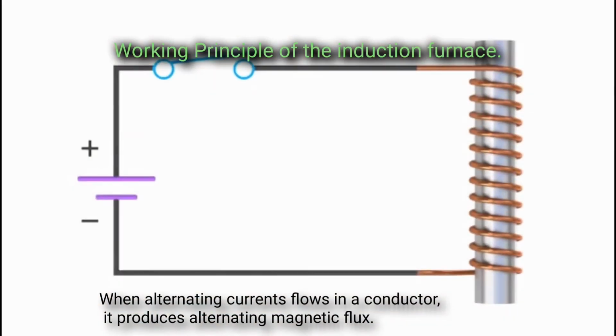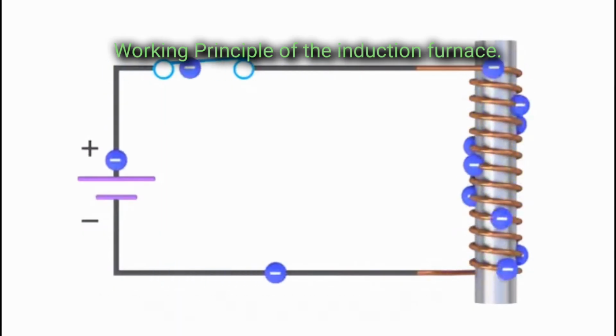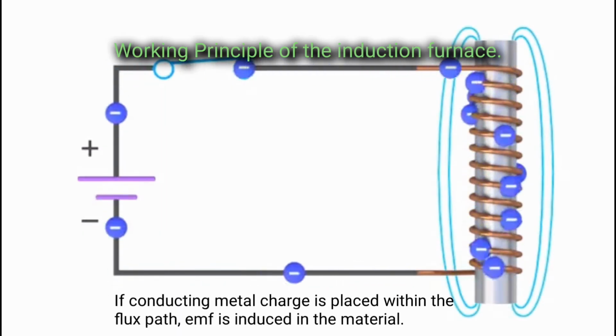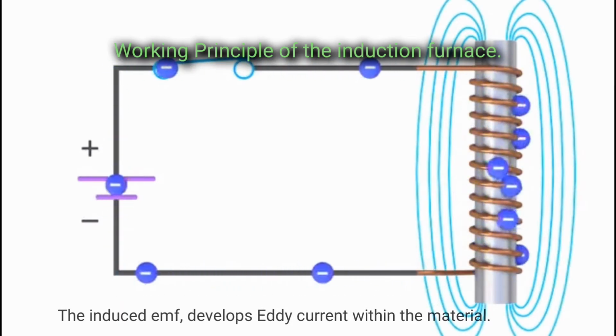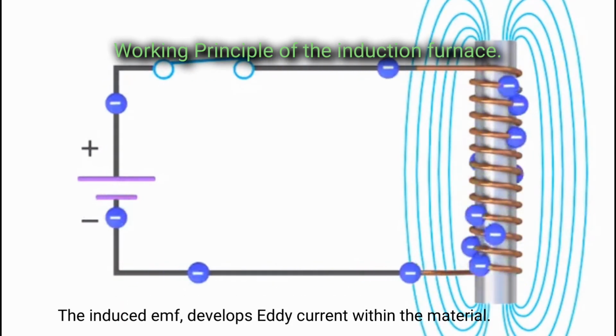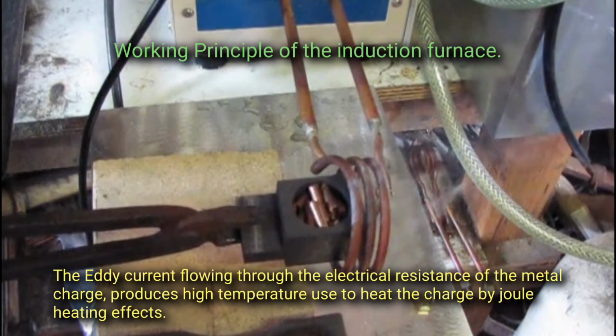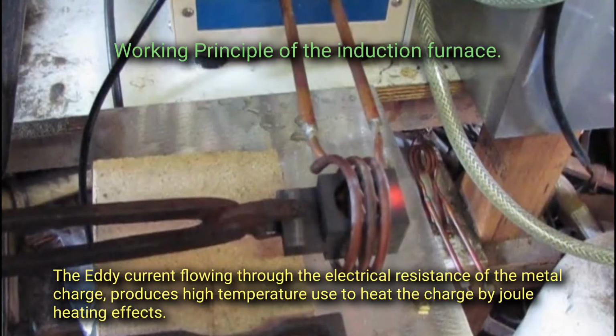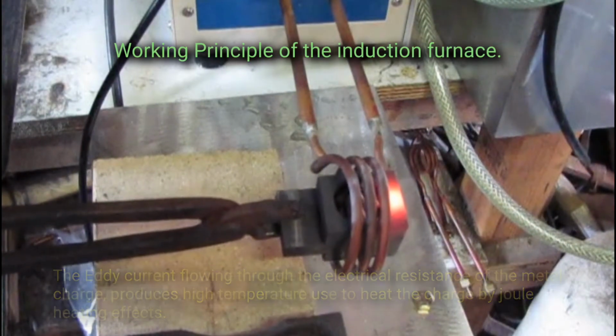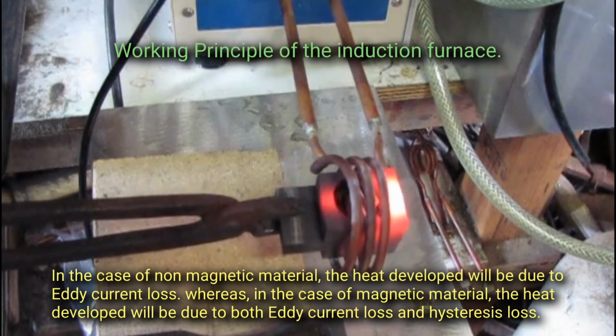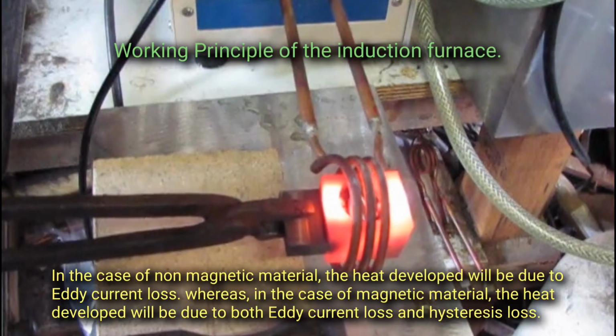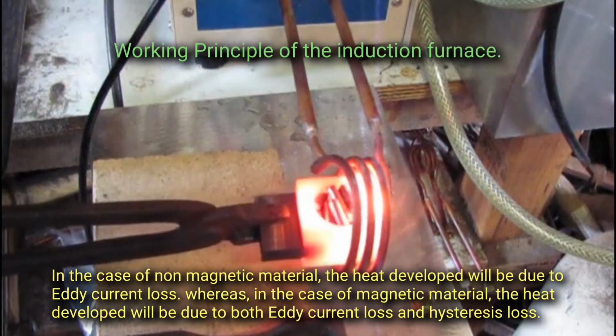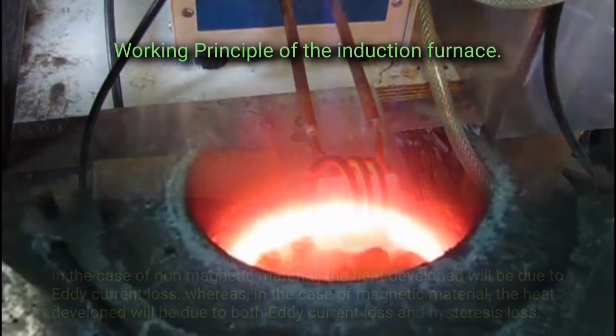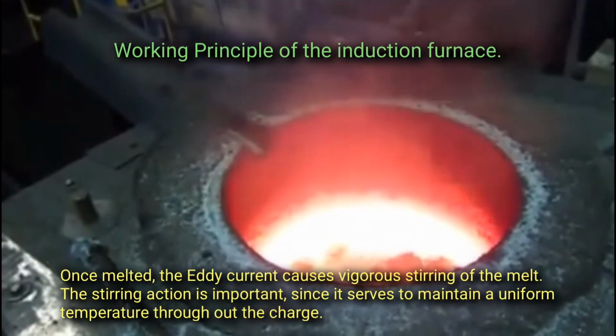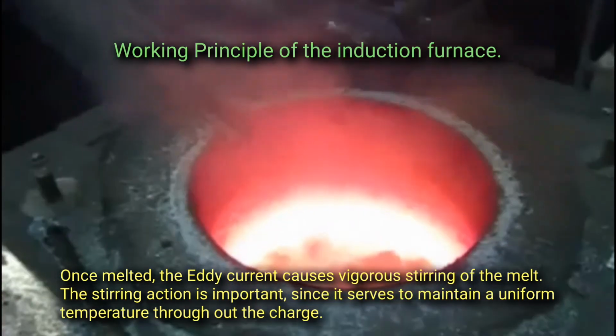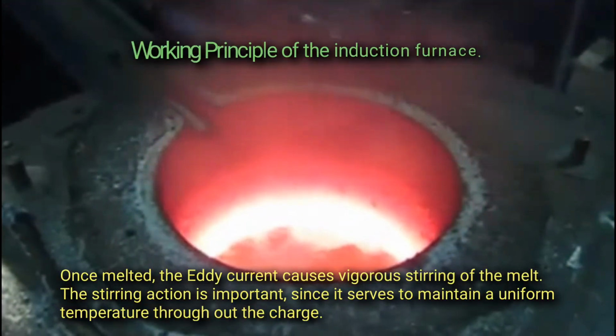When alternating currents flow in a conductor, it produces alternating magnetic flux. If conducting metal charge is placed within the flux path, EMF is induced in the material. The induced EMF develops eddy current within the material. The eddy current flowing through the electrical resistance of the metal charge produces high temperature used to heat the charge by Joule heating effects. In the case of non-magnetic material, the heat developed will be due to eddy current loss. Whereas, in the case of magnetic material, the heat developed will be due to both eddy current loss and hysteresis loss. Once melted, the eddy current causes vigorous stirring of the melt. The stirring action is important, since it serves to maintain a uniform temperature throughout the charge.